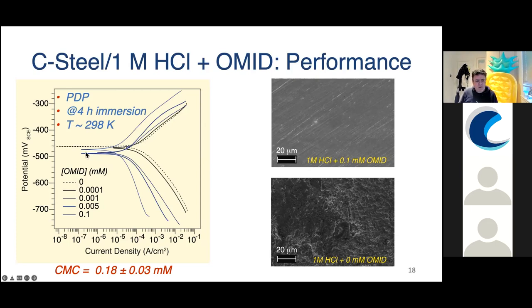Also, the potential doesn't change very much. It changes within 50 millivolts, and that's considered a mixed inhibitor. So the OMID, under these conditions, is acting as a mixed inhibitor, acting on both the anodic and cathodic reactions. And to be honest, quite typically, under these sort of acidic conditions, most organic corrosion inhibitors are mixed type inhibitors.